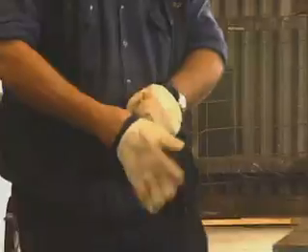If steel, tin, aluminium, anything goes into the furnace, it causes a great deal of havoc. The quality of our rod is very poor. In the case of aluminium, the furnace actually blocks up and it becomes like glue, and we can't get the copper out. It could be weeks before we actually clear it. So no foreign material in the way of metals is allowed into the furnace.